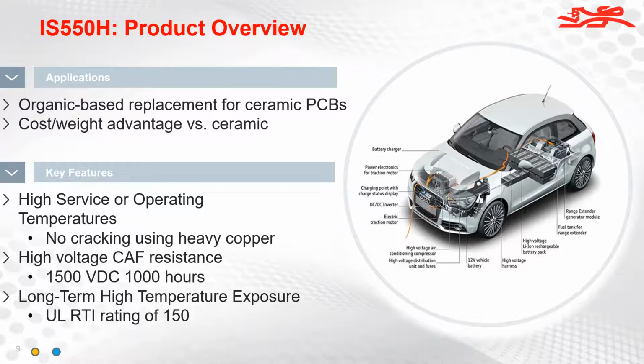Under high voltage, CAF resistant conditions at 1500 volts, I mean, what we're seeing now is voltages in the 400 to 800 range, but there's discussions about even operating at up to 3000 volts for these fast charging systems. And so that's an area of discovery that we still have to work on, mainly because the systems to test the material up to those levels is non-existent for the most part in the industry.